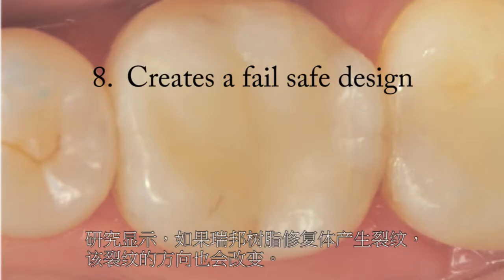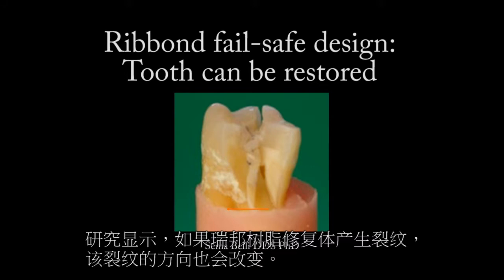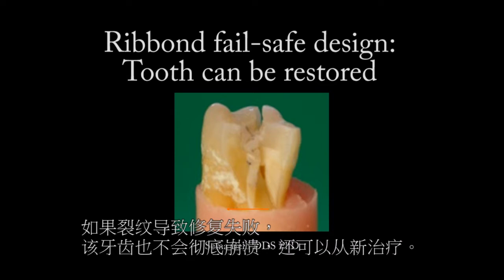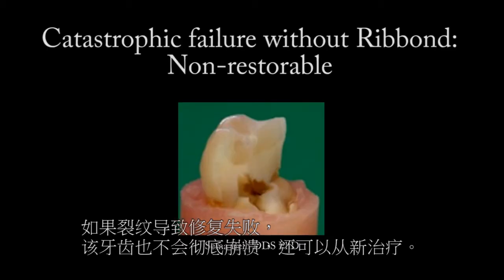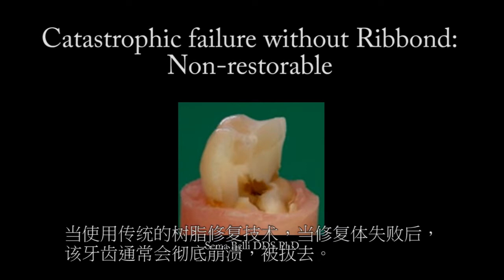Fail-safe design. Studies demonstrate that if a crack starts in a Ribbond composite restoration, the crack is redirected. If a crack leads to failure, the restoration tooth complex fails safely and the tooth can be retreated. In the case of standard composite restoration techniques, when the restoration tooth complex fails, it tends to fail catastrophically and the tooth must be extracted.